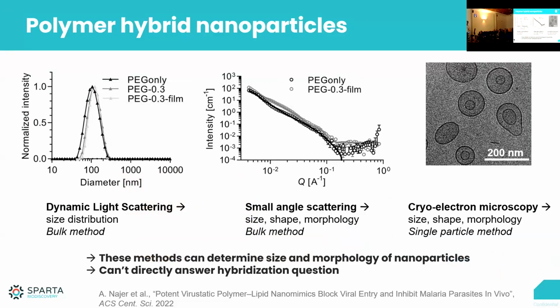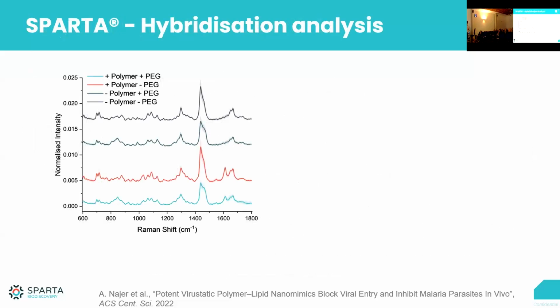We have some standard techniques here, such as DLS, for instance, and some small angle scattering and cryo-TEM. But whilst these are very quick, well, not cryo-TEM, but DLS at least, to analyze whether you have a reasonable population of nanoparticles, you can't really look at the hybridization from here. Sometimes you can get an indication of that from the cryo-TEM, but it's quite difficult. But of course, from a compositional perspective, we can see this quite clearly.